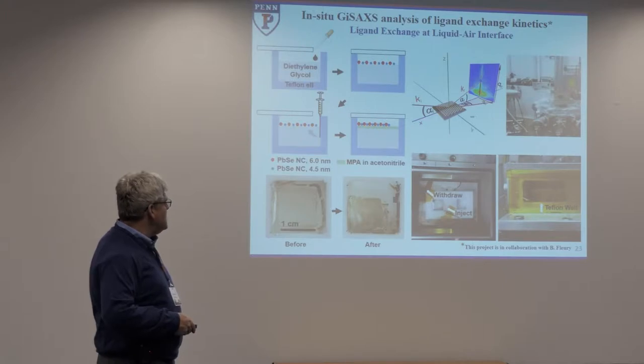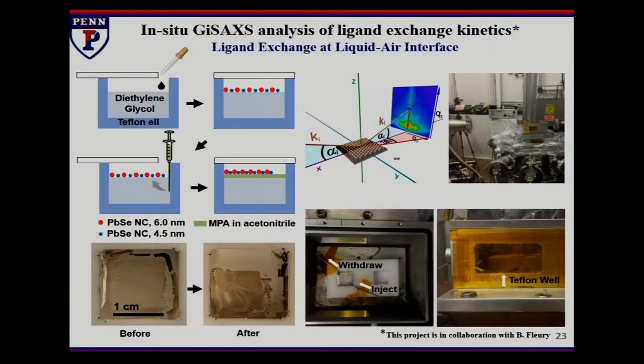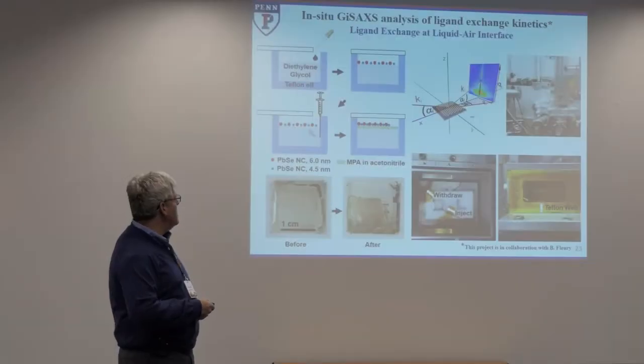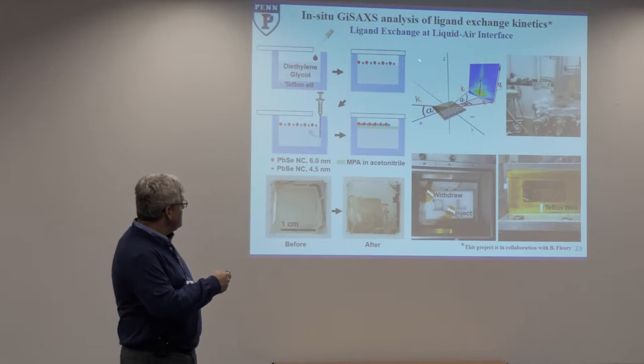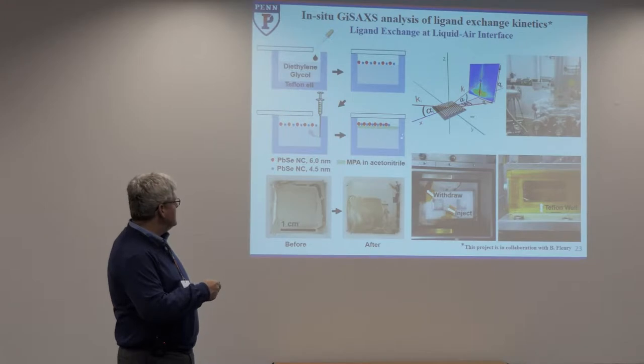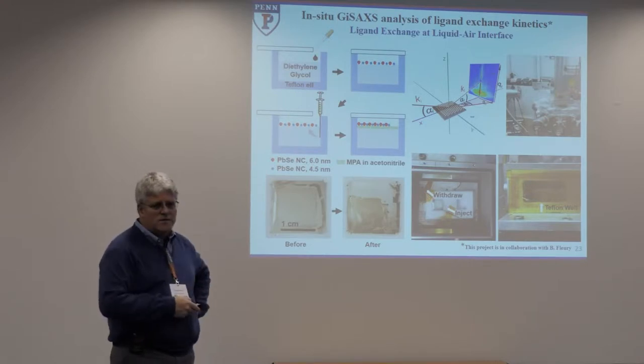Let me go a little further. This exchange process is something that we care a lot about. So we set up a fair number of experiments to try to better understand the kinetics and what's involved. This is kind of the extreme of complicated experiments. It is a synchrotron-based experiment where we produce films of these materials at an interface, introduce the new ligand underneath, and allow it to start exchanging the environment of the particles, and then we watch that in real time with grazing incidence X-ray scattering. So a lot of work for this piece.